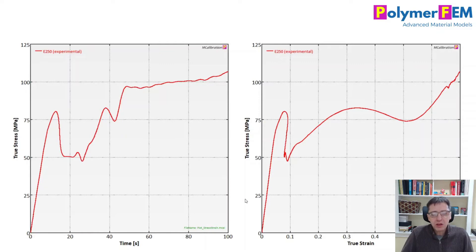If we plot the strain and stress at the center of that element, we'll see this curve. And this is really interesting to me. See that the yielding occurs here. And then we have the unloading that I talked about before. We have a substantial unloading here. The stress goes back here.